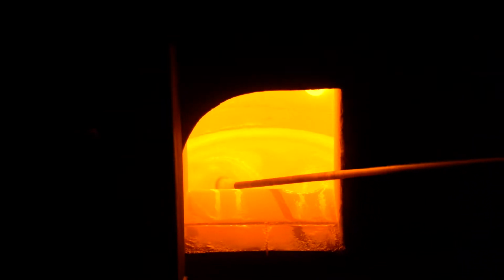So what we have here is the last melt going into the furnace, and this is a little bit of an insight into what's really happening in this transitional phase of all these ingredients and how they transition into glass. So quite often we talk about melting glass from its raw materials. What we're actually really doing is creating an environment very alkalinic. So the soda within the mix creates a very alkalinic environment which actually dissolves the silica in this process.